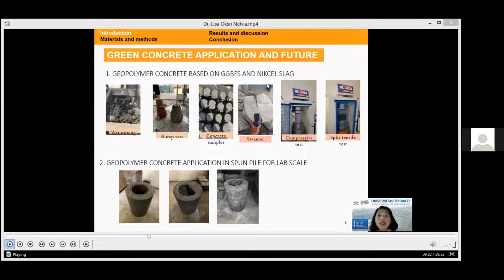The observed composition for the experiment is 50% NSP, 50% GGBFS without any cement, with different molarity. Samples are cured at 60 degrees with a steamer for 4 hours, and the compressive strength of the geopolymer concrete with 4 molarity and 8 molarity at 28 days is around 6 and 7 MPa respectively.